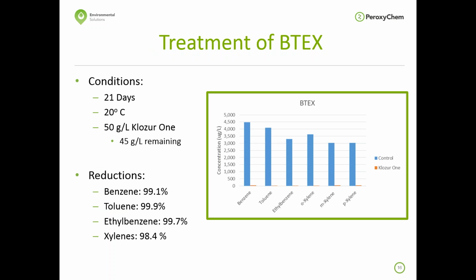So just to start showing some of the efficacy data that we have using Klozur One, I have a series of a couple of slides here looking at different compounds, and this is just your general BTEX compounds, a single time point taken after 21 days. The experiment was run at 20 degrees C with 50 gram per liter Klozur One. After 21 days of reacting with these compounds, 45 gram per liter was remaining. Actually, the sodium persulfate was remaining afterwards. The reductions, as you can see, were quite substantial. Benzene by 99.1%, toluene by 99.9%, ethylbenzene by 99.7%, and xylenes, the different xylenes, ortho, meta, and para-xylenes, were all degraded by an average of 98.4%.